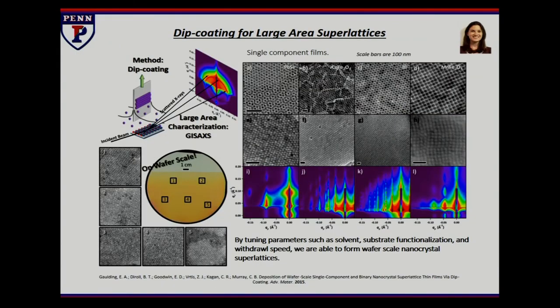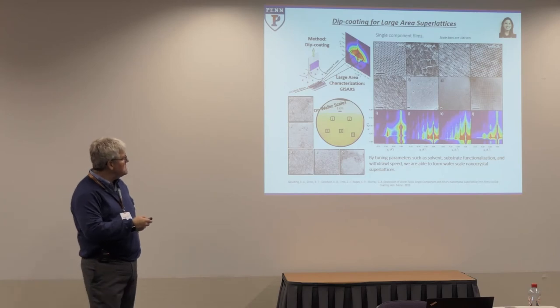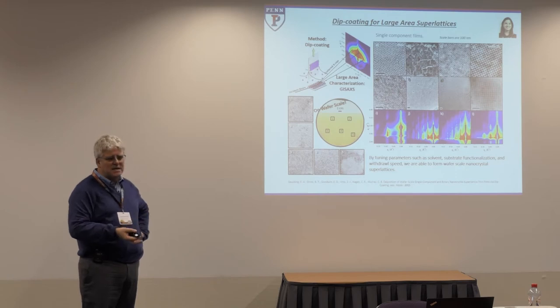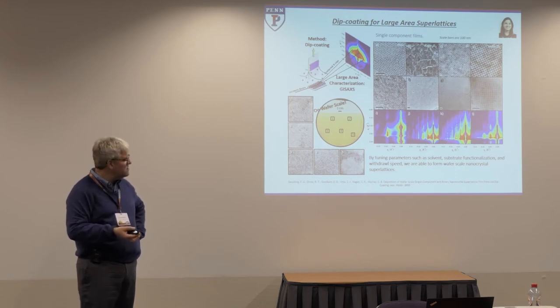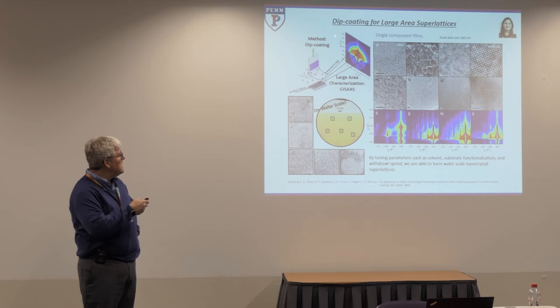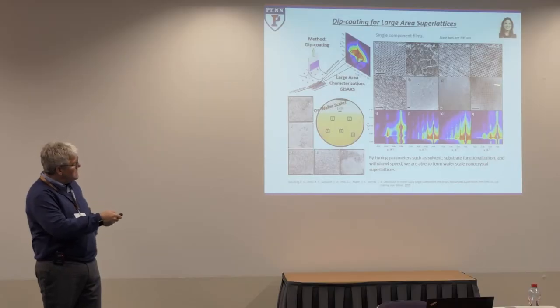All right. Where we move now with these kinds of processes is to go to robotic handling. So now we do the growth of these types of systems using, generally, you can do spin-on coating, but the length scale of ordering there is still fairly short range. If you do a slower process, like dip coating, where you have a mixture of the constituent particles in a solution, and you dip a wafer in, or plastic substrate, and then withdraw it slowly, then you can control the drying rate so that these superlattice domains grow over the surface of the wafer.